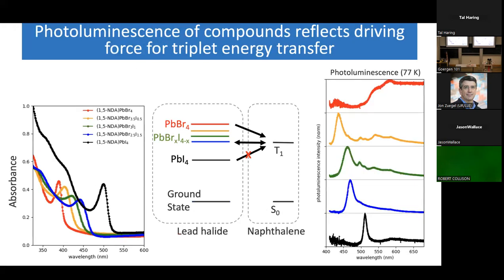And when we look at the photoluminescence from this series of perovskites, what we find is that it's essentially consistent with our expectations. The pure bromide system shows mostly naphthalene triplet-based emissions. That one's shown in red. For the pure iodide system, we see only emission from the inorganic exciton because there is no triplet transfer to naphthalene. And then for some of the intermediate combinations, we see both inorganic exciton emission as well as naphthalene-based emissions.